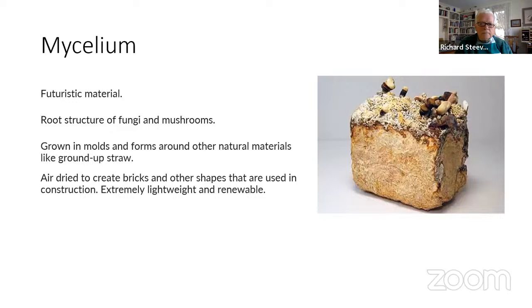So this is a material that can be grown into bricks. The root structure of fungi or mushrooms is grown in molds, and it actually forms around other natural materials like straw, and you can form bricks from it, and then air dry them and use them as bricks and cement them together, right? That's cool. So very lightweight, renewable, other than the mortar that you would use, would completely eliminate the production of CO2. In fact, the formation of the brick itself would undoubtedly consume CO2.